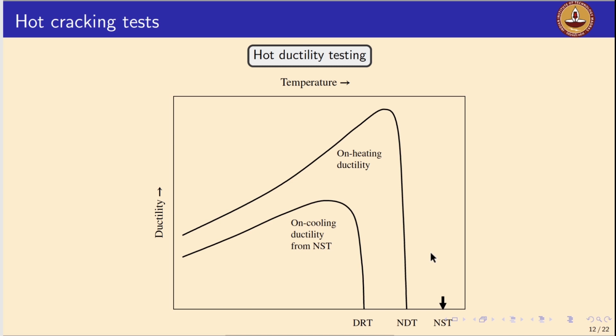Right, so we take the samples from the candidate chemistries and we identify hot ductility as a function of temperature. Right, three important temperatures we have to identify. So the first is the nil ductility temperature, the temperature at which the material loses its ductility completely. And then subsequently, by increasing temperature stepwise, we can also identify the temperature at which the material loses its strength as well. So the difference between NDT and NST can give us an indication about whether liquefaction phenomena is predominant when the material is heated up to various temperatures during welding.